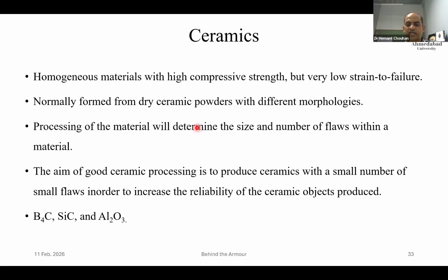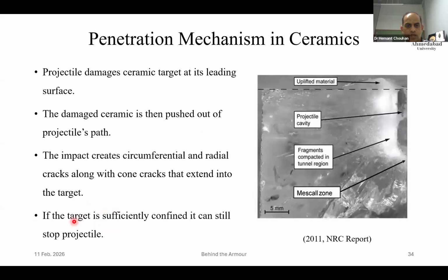If not done satisfactorily, then your fourth onwards bullet will perforate the laminate. And the best of the ceramics are boron carbide, silicon carbide, and aluminum oxide. Though this one is preferred for blast, it is not preferred for personal protection because of its low efficacy compared to these two and higher density compared to boron and silicon. Now, what makes and how the bullet stops?